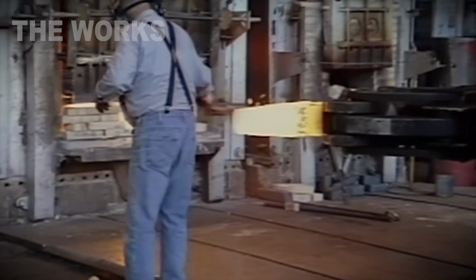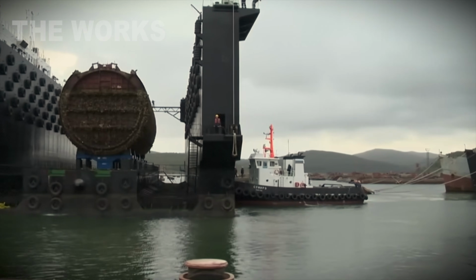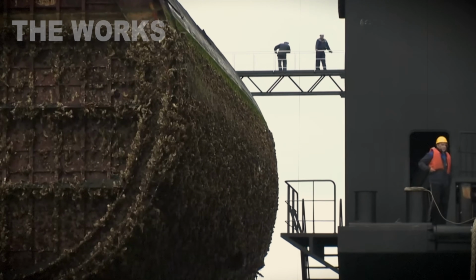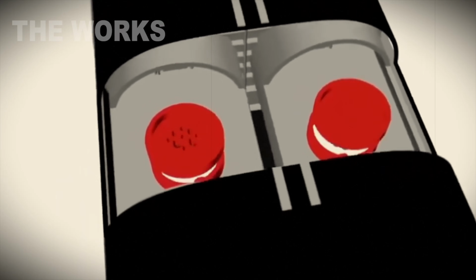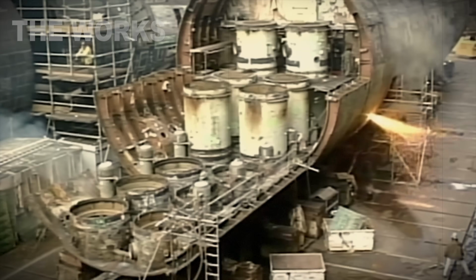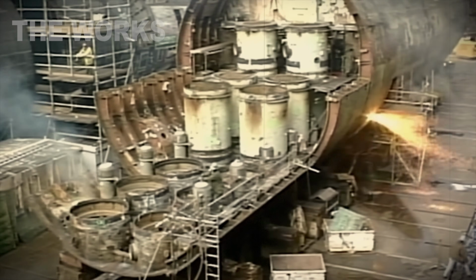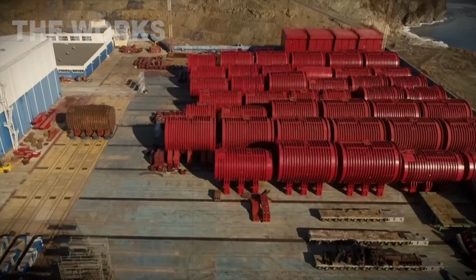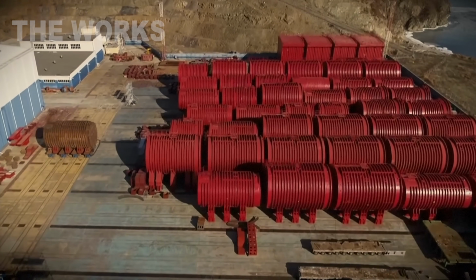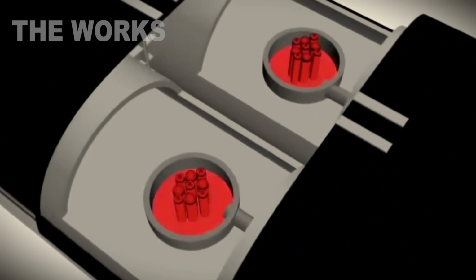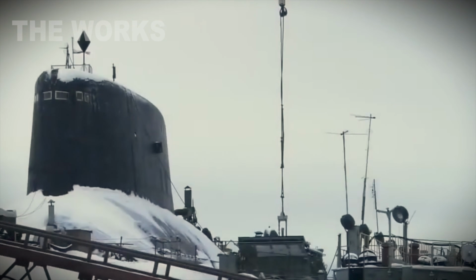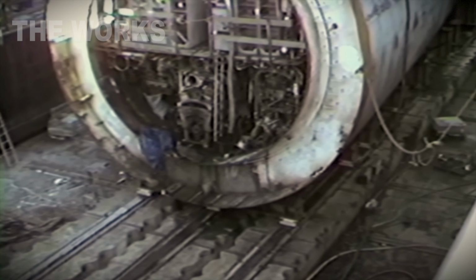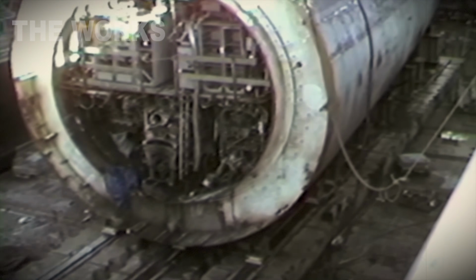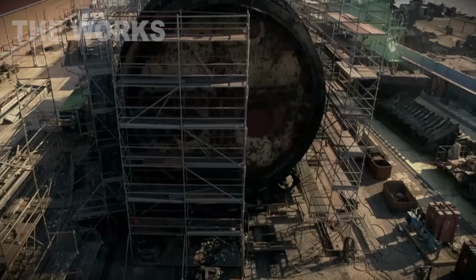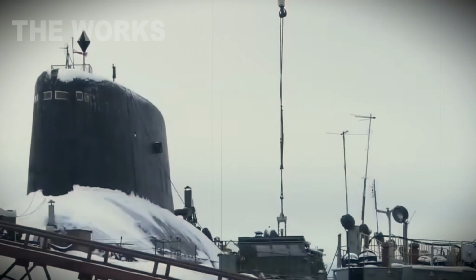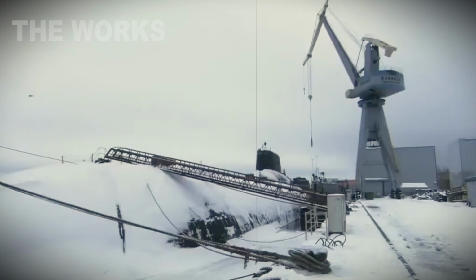Inside the reactor core are fuel assemblies. They've kept this monster alive for decades. Each assembly is a bundle of thin zirconium tubes, about half an inch in diameter. Inside, uranium dioxide pellets. One assembly is 13 feet long. Weight, 660 pounds. The reactor holds 100 to 120 of them. They're removed using remote manipulators. Each assembly emits a lethal dose of radiation, 500 roentgens per hour at 3 feet. That'll kill a person in an hour.